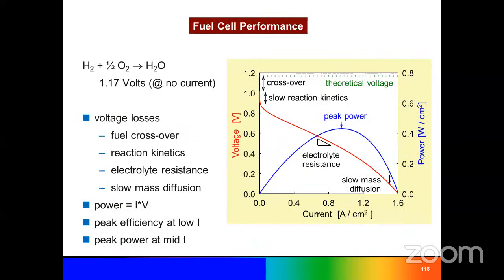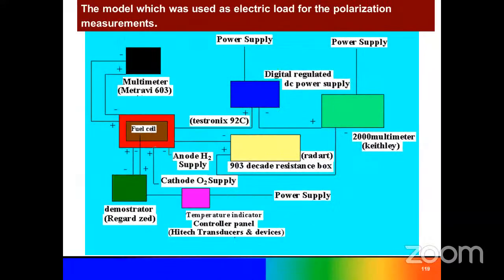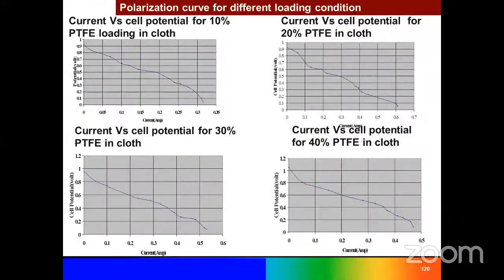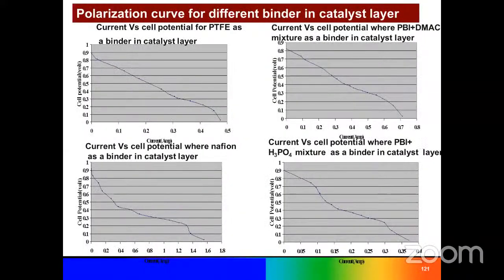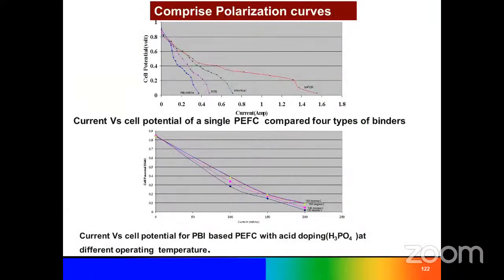And then finally we check the current density and voltage of this fuel cell. This is the fuel cell measurement circuit. And then finally we optimize the doping percentage of the PTFE, where we found that around 20% PTFE is giving the maximum hydrophobic property of these materials.